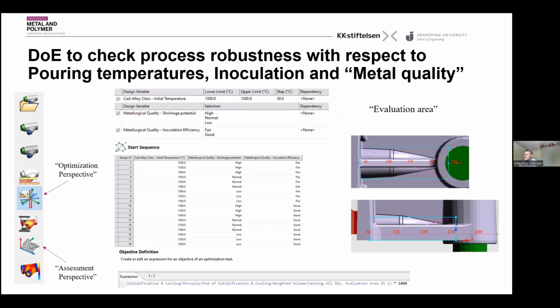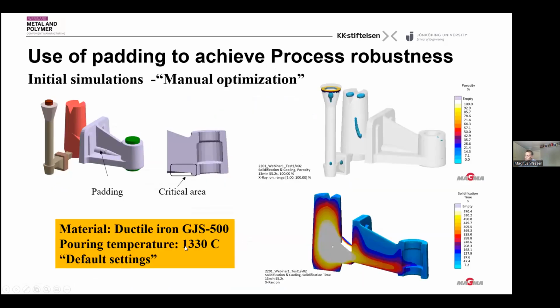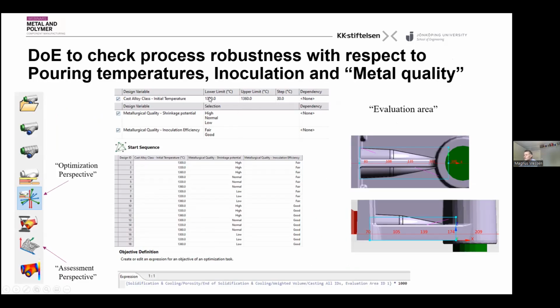Of course, you can then easily set this up with an extremely small amount of work. In the program, in Magma, you can go into what is called the optimization perspective. If you have designed your part, you have maybe the CAD and the mesh and everything is set up, you can easily go into the optimization perspective. And then you can tell what your design variables are, what is varying in the process. For instance, in this case, the foundry, from the first flask to the last flask, if you're making several pourings from a ladle, might vary maybe 60 degrees. So I said, okay, let's see what happens if we run, instead of 1330, which was my target and good pouring temperature, down to 1300 or up to 1360, in steps of say 30. So that means 3 simulations.